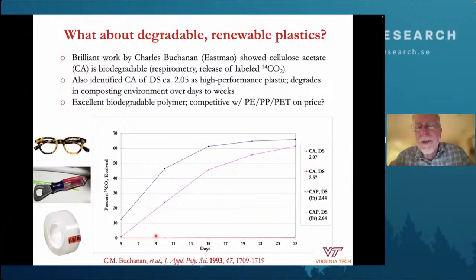But Charles did this wonderful experiment of radio labeling cellulose acetate at the ester group, and then putting it into a composting environment and following labeled carbon dioxide that was evolved. And what you can see is that this was for several cellulose esters, so you can't really see, but the cellulose acetate propionates, both of them are down here on the bottom. So over the course of a few weeks, they're not biodegrading.